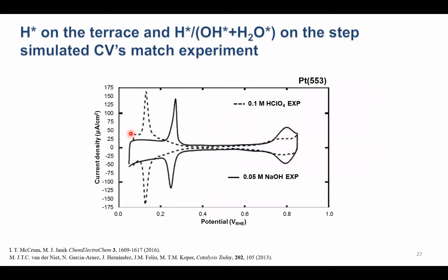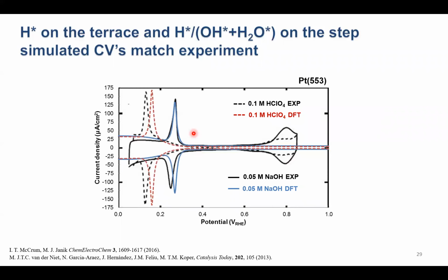And so now we can simulate CVs again, considering now the effect of the cation. Here we have the dashed line as the CV experimentally measured for platinum 553 in perchloric acid. The solid line is the CV experimentally measured on that same surface in sodium hydroxide. Again, what I've already shown previously, we can match the CV in acid with DFT. And now if we consider this effect of the cation coming close to the step and weakening OH and water adsorption, we find that also matches experiment very nicely. And so this seems to support that our hypothesis was correct. The cations can sit close to the surface, and once they're there, because they retain most of their charge, they interact strongly with adsorbed species like OH and water.